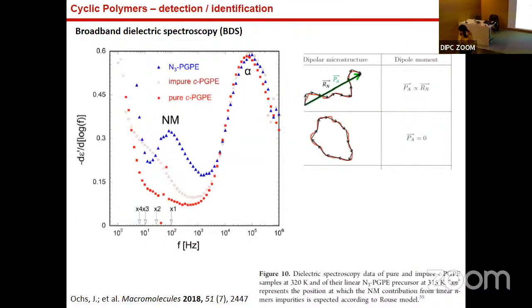And this is more recent. This is by using broadband dielectric spectroscopy. We implemented this to identify the formation of cyclic polymers. This is true only in linear polymers, for example, a linear polymer where we have all the monomers oriented in the same direction. This means, in chemistry words, a regular polymer. It should be a polymer that shows what is called normal mode relaxation. What is a normal mode relaxation? It is related to the fluctuations of the end-to-end vector of a linear chain. Not all polymers show that, but this polymer, and specifically this polyether, shows this end-to-end vector.